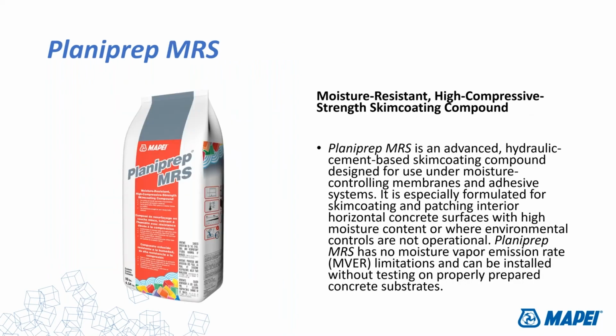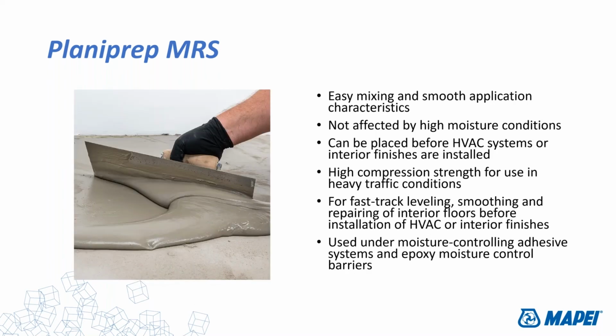Another product we've had out for a couple years now is Planiprep MRS, Moisture Resistant Skim Coat. Again, this is like Quick Patch in that it's got all this hydraulic cement and it works extraordinarily well on high moisture concrete slabs, but it does not contain any sanded material. So you can apply this in a thinner layer, smooth across the surface to make a skim coat application over high moisture concrete slabs.